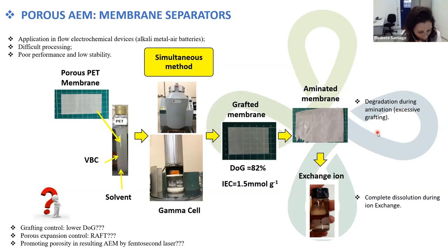For the preparation, we tried pre-irradiation and simultaneous irradiation. You have obtained some degree of grafting by using the simultaneous method, probably because you have a rapid recombination of the radicals in PET material. So you have obtained grafted membranes with a good DOG and a good IEC. But when you put our membranes through the functionalization process, you have observed degradation during amination. Maybe because I have an excessive grafting. And then, curiously, you have complete dissolution during ion exchange. I mean, when I was changing from chloride to hydroxide.